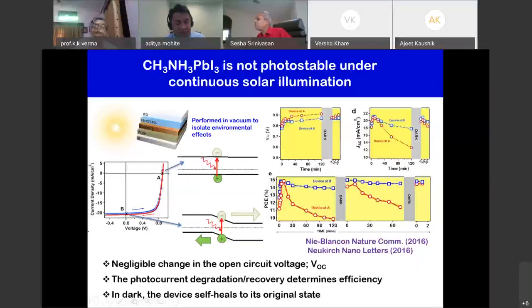You have a solar cell that was made, and we measured the photovoltaic device at point A, the open circuit voltage, and at point B, the short circuit current. We looked at the open circuit voltage as a function of time: you turn the solar simulator on and let it go. What we found is that the voltage is fine. It increases in the beginning, but then remains quite flat. It does not really degrade if you turn your solar simulator off and come back again.